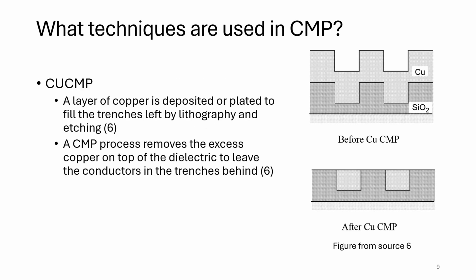For copper chemical mechanical planarization, sometimes referred to as copper damascene, the slurry typically includes an oxidizer to form a soft copper oxide, complexing agents to keep ions suspended in solution, and corrosion inhibitors to prevent pitting of the metal. Mechanically, we can tune pad hardness and pressure to limit dishing in wide copper features while still clearing the wafer.